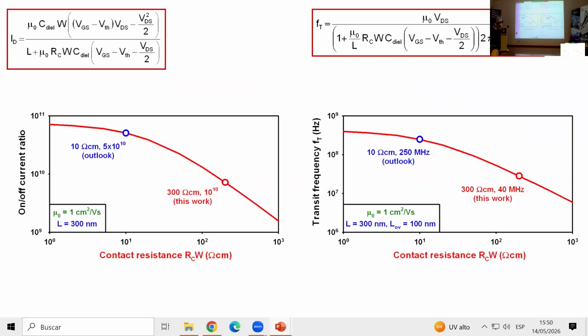And in the final slide, I want to put this into perspective. So on the left, I'm again plotting the on-off current ratio as a function of contact resistance, and on the right, I'm plotting the transit frequency as a function of contact resistance. And to produce these two plots, I'm again using the two equations that I've shown earlier, the one for the maximum on-state drain current in the first part of my talk, and then the one for the transit frequency in the second part of the talk. And what we see is that, not surprisingly, as we reduce the contact resistance, the on-off current ratio of the transistor improves. So this is where we are now. This is what I've just shown you.